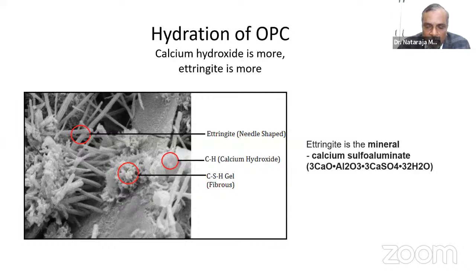So we need to decrease this calcium hydroxide, but as long as you have OPC alone to the extent of 100% in your concrete, it is extremely difficult to avoid it. So this is really not a material required from the point of durability. Also, we have one more important compound, especially calcium aluminate. Though we keep the calcium aluminate to less than about 10%, this calcium aluminate, along with some of the sulfate compounds, because many a time the concrete will be exposed to a marine environment, and in fact we have acid attack coming into the picture, we have sulfate attack coming into the picture, and different types of sulfates reacting with gypsum. And of course, with calcium aluminate, over time, we get a material called ettringite.